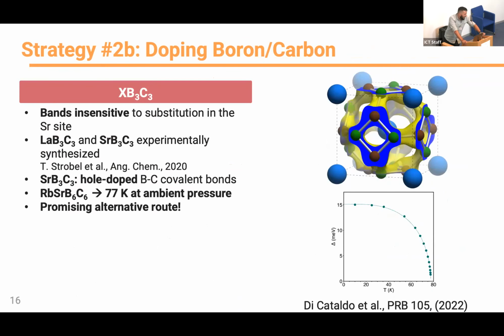Now, just because I have one more minute, I would like to mention another alternative strategy to doping, which does not involve hydrogen. This is a boron-carbon system, and it's interesting because it forms a sodalite-like structure very much similar to that of calcium H6 that was discussed this morning. In this structure, the boron and carbon are covalently bonded, and they are wrapped around, again, an electropositive atom, which is donating charge to them. These were experimentally synthesized with lanthanum and strontium as metal atoms. And as long as you use a trivalent atom like lanthanum, the system is insulating.